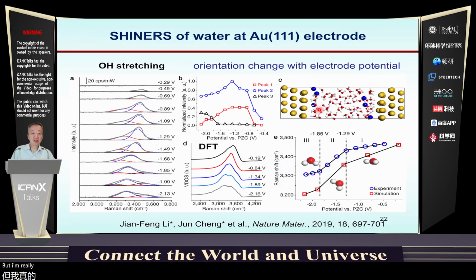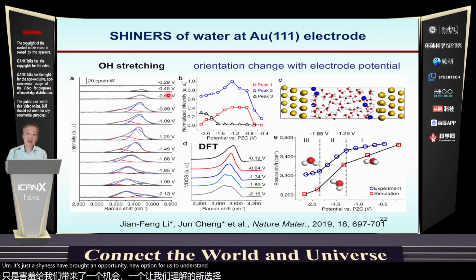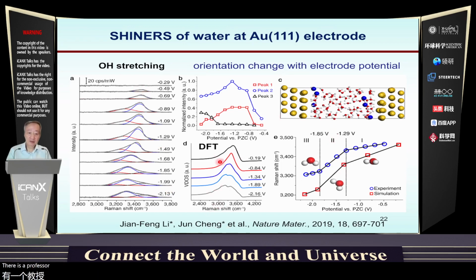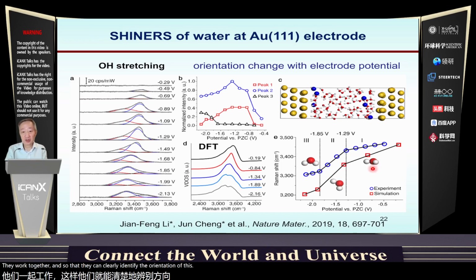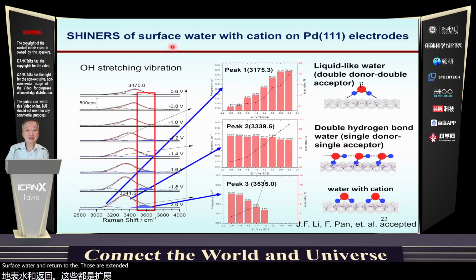But I'm really interested in this one because surface water is so important. SHINERS has brought a new opportunity for us to understand or to classify the orientation change with the applied potential. As you can see, when we change the applied electrical potential, the SHINERS spectrum changes dramatically, which provides a hint and is also related to the DFT. That's Professor Jun Cheng's specialty, expertise, so they work together and can clearly identify the orientation of this surface water. And recently, they also extended this study from gold to palladium 111,